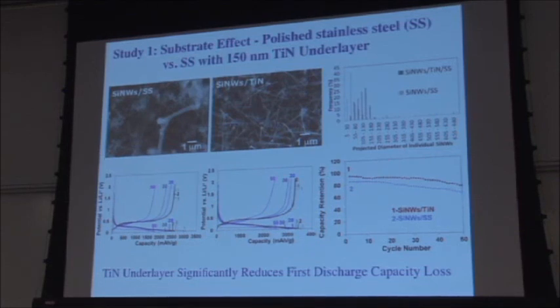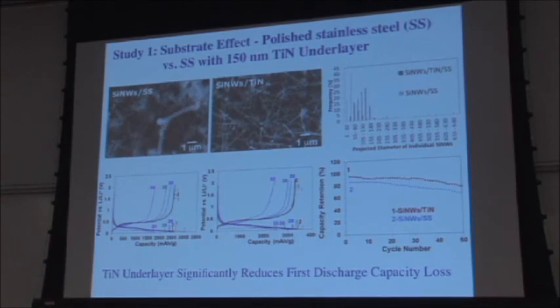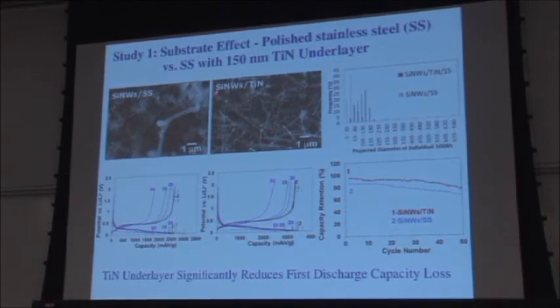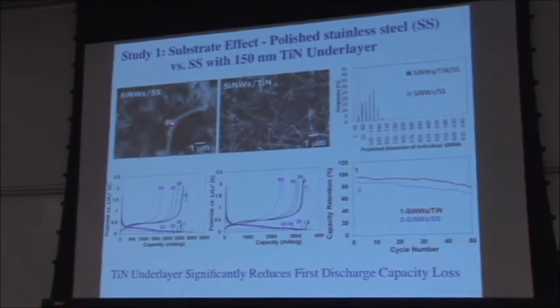And there's two reasons why this occurs. First of all, these large nanowires, which hold a lot of lithium, it's been really shown, well documented in literature, that upon first lithiation, they literally just disintegrate. So they fracture. And the critical diameter seems to be, from calculations, about 200 nanometers. So the big nanowires that hold silicon disintegrate, so they stop after first lithiation, they're gone. And at the same time, you build up a lot more SEI layer relative to the bulk lithium content in the really fine silicon nanowires versus the coarser ones.